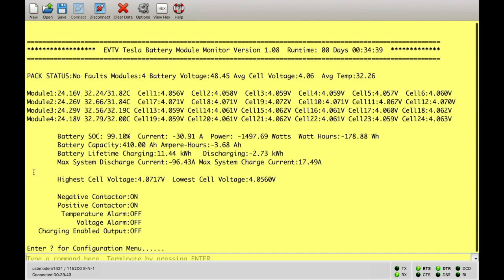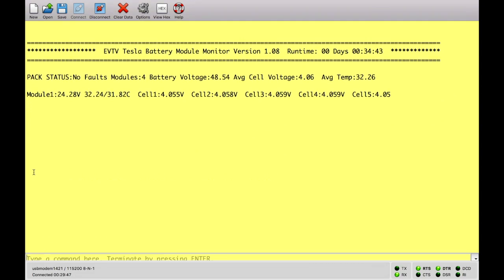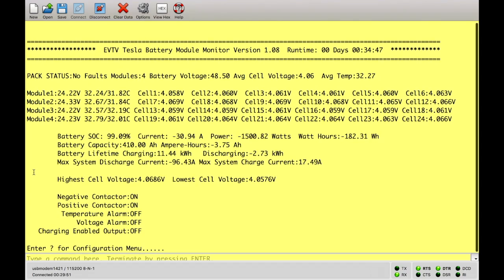Their world in the inverters and their world in the charge controllers is based on the 2.1 volt lead acid cell. And you have 6 of them in a 12 volt battery, 12 of them in a 24 volt, 18 of them in a 36 volt, and 24 of them in a 48 volt. We're dealing with nominal 3.6 volt cells, and so 6 of them gives us about 21 volts nominally. 12 of them gives us about 42 nominally, and fully charged about 48. They typically charge the lead acids to 57, or with equalization as high as 64 volts. So we're slid down the range a little bit from what they're accustomed to seeing.